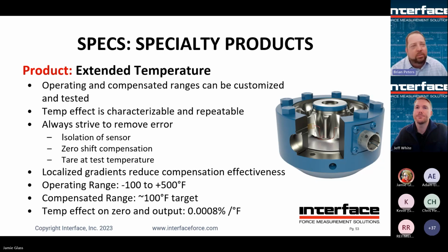Also to keep in mind here, sorry, Jeff, I'll run with this. There's a cutaway in this model, and if you look to the left of the cutaway there's a little bit of a pocket. It's important to note how a sensor is actually temperature compensated. We have specs that tell you it's going to meet a certain level of temperature change, but you need to remember that's assuming a homogeneous temperature profile. If you have a localized temperature gradient, maybe coming through the load string, which then transfers through the center hub, through the beams, and eventually reaches the outer ring, that's very different than if the whole load cell is brought up to temperature.